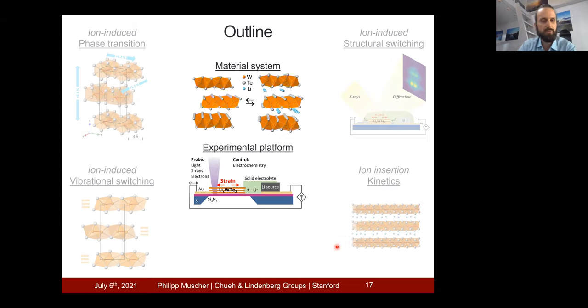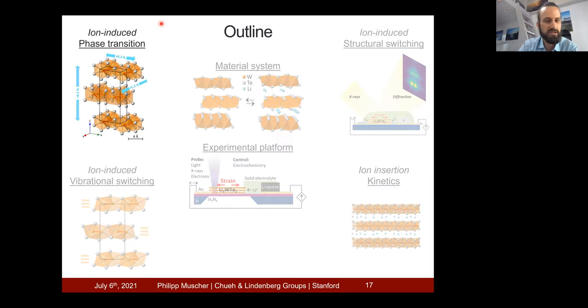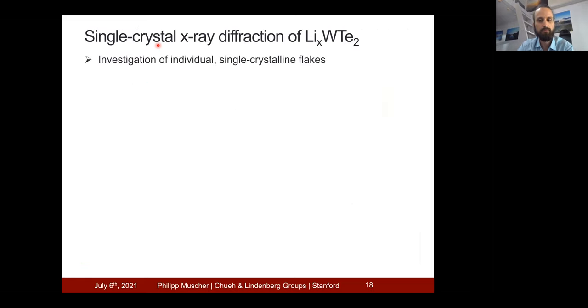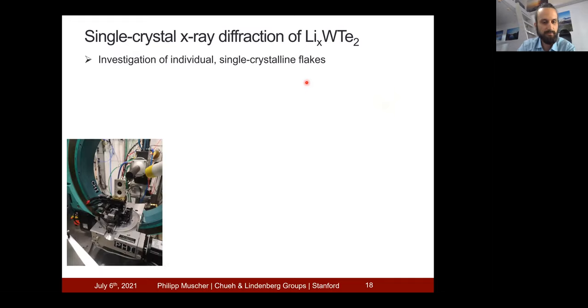So now that I've shown you the experimental platform, I'd like to come to the phase transition that I already alluded to, because we saw some signature of it in the electrochemistry. For this, I'm using a technique called single crystal X-ray diffraction. This technique allows the investigation of the crystal structure of single crystalline particles. For this, I'm using synchrotron X-ray radiation. So essentially, we use a 100 meter diameter electron accelerator, which then generates X-rays, which come out of this tube, and then they hit our individual tiny tungsten ditelluride flake, which is located in this holder over here.